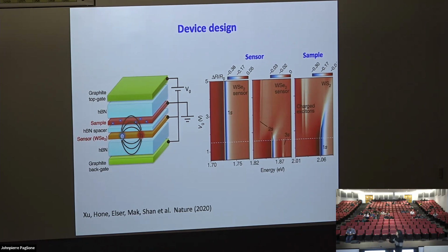But of course, experimentally there's a challenge because 3s is much weaker, the signal to noise ratio will be worse, things like that. Okay. So we keep our design such that we fix the spacer on the order of 1 nanometer-ish, and we are going to focus on the 2s only.